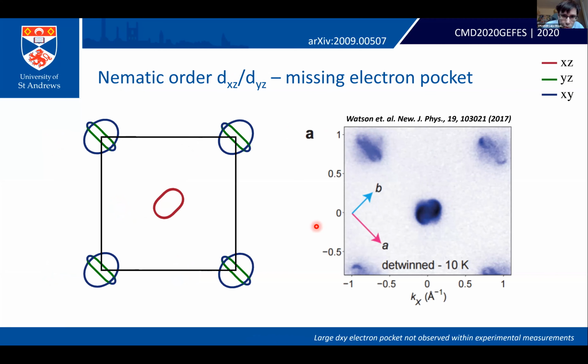But you may notice, within this theory of nematicity, which purely involves the XZ and YZ states, the model predicts a second large electron pocket of mainly dxy orbital character, which has not been observed within the experimental ARPES measurements. Now, this has been quite confusing and caused a lot of disagreements within the literature, and it's even been given its own name, known as the missing electron pocket. And so we really wanted to understand what has happened to this missing electron pocket, comparing the theory and the experiment.